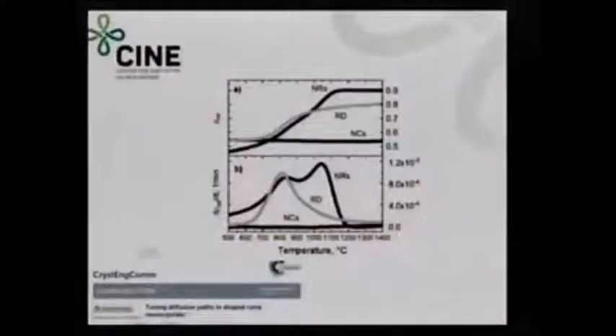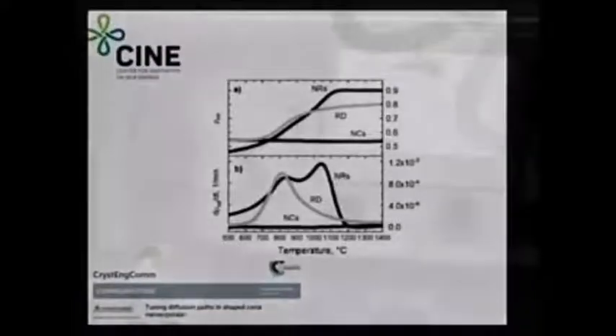So we've done some experiments with the nanorods, nanocubes, and we compared that with random nanoparticles, and we came up with very interesting results. Our nanorods sinter for ceria-based materials at rather low temperatures, like 1,000, 1,100 degrees C. This is rather low for ceria-based oxides, and they reach very high densities, up to the theoretical densities.